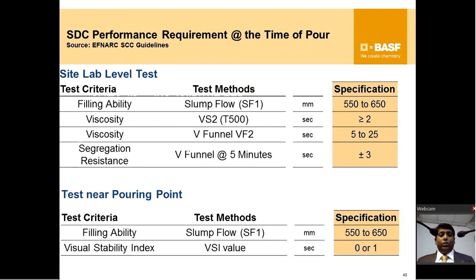So just to give you the site scenario: at the time of pour, after 2 hours or 2.5 hours, when you're just about to pour, if you have a lab at the site, these are the tests you need to do. Check for the filling ability. You should have something between 550 to 650 mm. It is okay. You have to check all these three, 1, 2, 3 are important. Viscosity, VF2 value between 5 to 25 seconds.